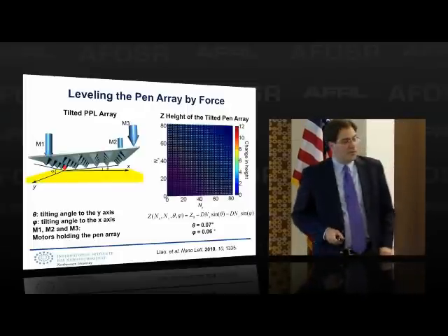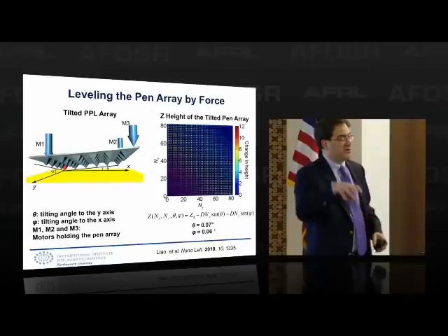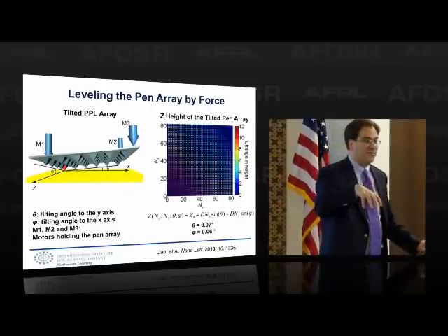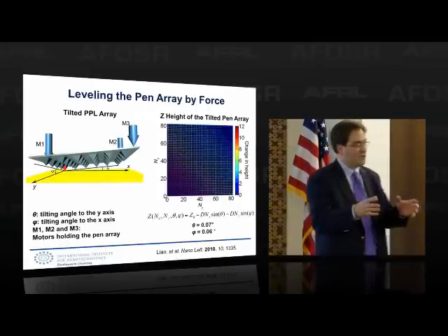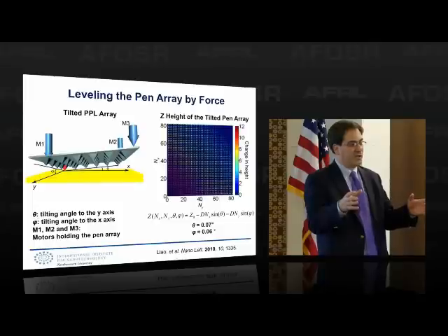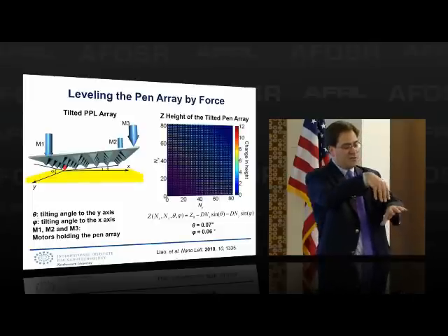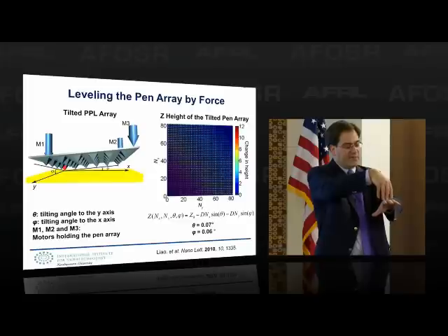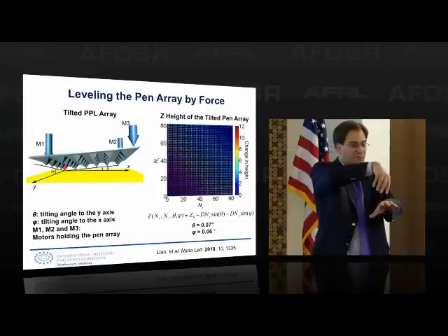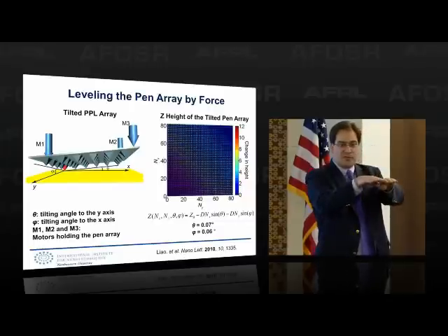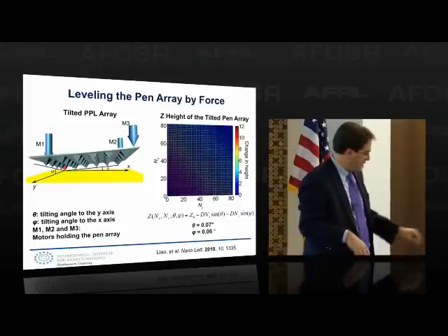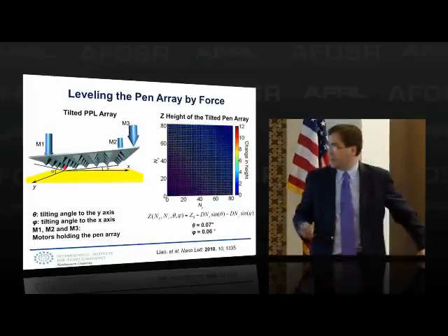Here's the real thing you should be thinking about, for the aficionados thinking about what the problem potentially might be here. Remember I told you that leveling is really important, right? I have this problem where even if it's perfectly level, not all the tips are in contact. But I have this problem. If I bring down the array, one side might hit first. How do I get the whole system perfectly level? And so we began to think about that and in fact model it.